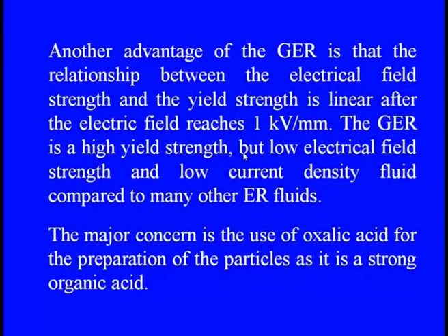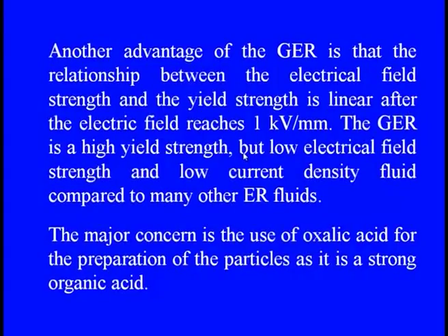And another advantage of the GER, the giant electro-rheological fluid, is that the relationship between the electric field strength and the yield strength is linear once the electric field reaches up to 1 kilovolt per millimeter. So, we can clearly see the linearity between the electric field and the yield strength up to a certain limit, beyond that not. And the GER has a high yield strength, but low electric field strength and low current density compared to the common ER fluids. The major concern is the use of oxalic acid for preparation of the particle, as we know it is a strong organic acid.